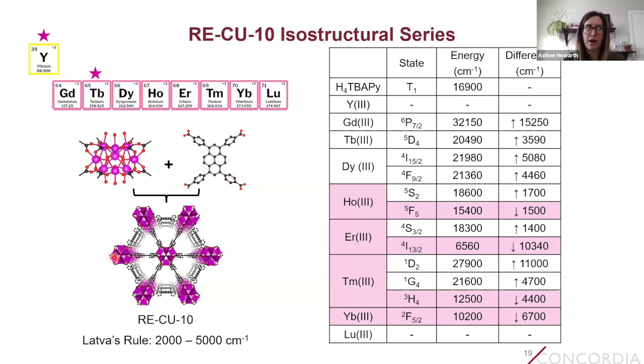And so it's a well-known phenomenon in the lanthanoid literature that when you have an organic ligand coordinated to a lanthanoid, whether it be a coordination complex or a MOF, if that organic linker has a triplet state that lies higher in energy than the emitting state of the lanthanoid that it's coordinated to, you can observe ligand to metal energy transfer and subsequent metal-based emission from the lanthanoid. And this would potentially be a competitive pathway with the generation of singlet oxygen, since the generation of singlet oxygen also goes through that same pyrene triplet excited state.